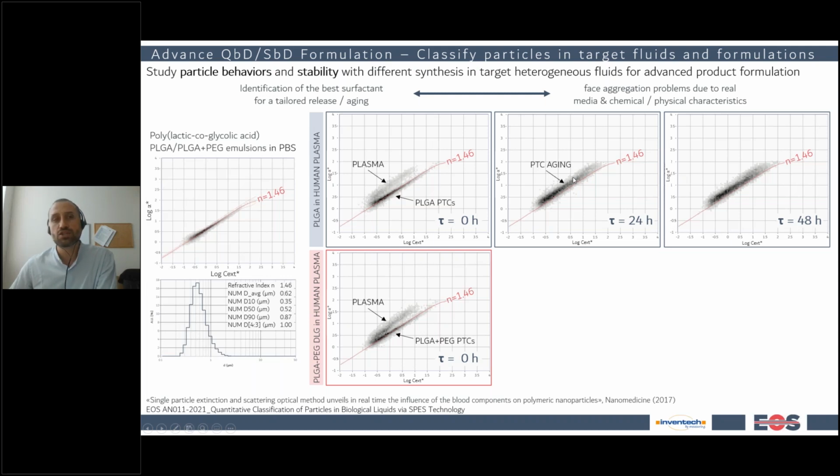So this means that they are changing their nature. In this case, they are absorbing water. So the structure of the particles changes, they become mesoporous from a physical point of view. The liquid in the surroundings penetrates inside the particles and lowers the effective refractive index of the whole particles, because it is an average between the polymeric and the liquid inside the particles.